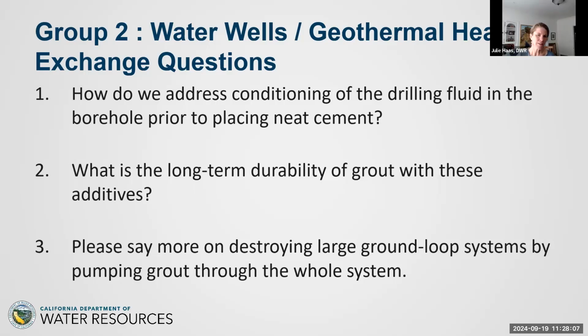So the next question is, what is the long-term durability of grout with the additives that you mentioned? Yeah, it's a very good question too. Let's start at the beginning then, just real quick. superplasticizer and welan gum, or say a retarder, are something that affects the rheology. These materials get used up chemically in the reaction. They don't appear anymore. So therefore, the main control over long-term durability still remains the water-cement ratio. That's the key thing, and the stability. These other admixtures and additives are short-term facilitations. They should not have an effect on the long-term set properties of the grout, including durability.